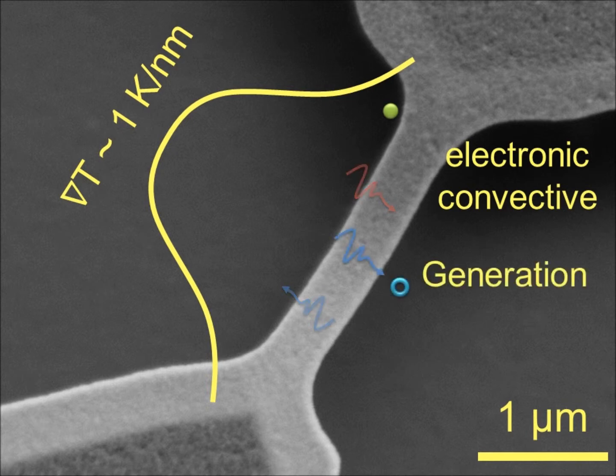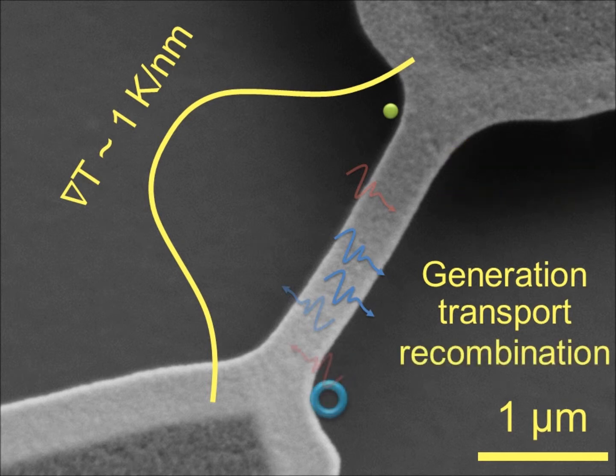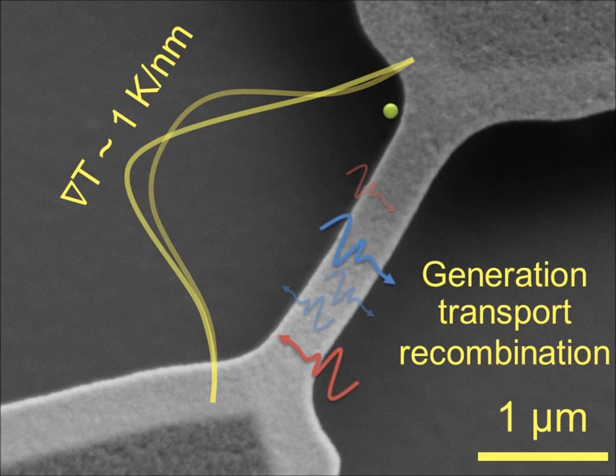More importantly, minority carriers, namely holes for this case, are generated in the hot regions of the wires and drift in the opposite direction of electron flow. As the thermally generated holes drift, their Peltier energy increases, leading to energy absorption from the lattice by holes. Once the holes reach the end of the wire at a lower temperature, they recombine and release energy. The latter process, called generation transport recombination, dominates over the electronic convective heat transport, leading to a skewed temperature profile towards the source of the majority carriers, namely electrons.